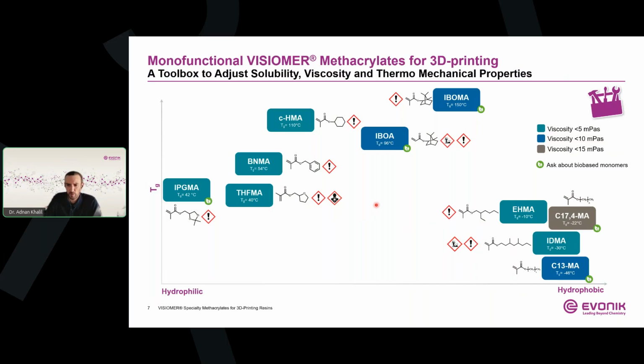our portfolio also contains more cyclic aryl and alkyl methacrylates with rather more bulky side chains and higher Tg values, which can be used to increase the hardness or the mechanical properties of the final polymer. For example, the IBOMA has the highest Tg of our portfolio with about 150 degrees Celsius.